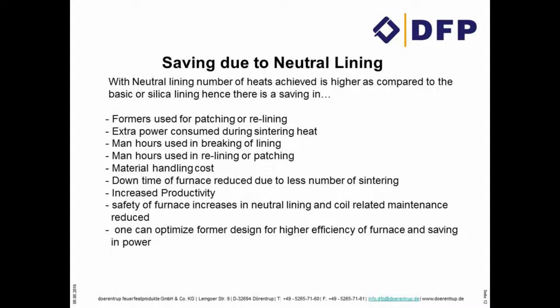What are the savings? As I told you, we can run the furnace continuously for say one week, and we can save on the former. Because with the silica lining, if you want to do 20 heats in a week, you have to go for either one or two patchings or two linings, whereas here with neutral lining you will be able to run for 70-80 heats. So you can run continuously for one week. You will be saving on your former, on sintering power, on man hours, on metal handling, even on downtime of the furnace. This in totality will give you the savings against the cost which you are spending for the neutral lining.